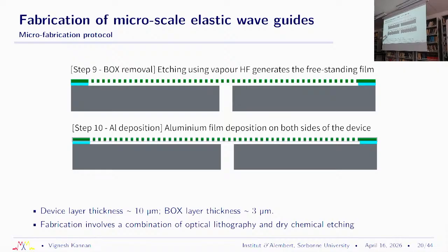Okay, so we end up etching the top surface, and it turns out that you can use hydrogen fluoride that basically gets rid of this intermediate box surface. So hydrogen fluoride, turns out, reacts not with the silicon, but with the silicon dioxide. And so what you end up with is a freestanding film with a 2 to 3 micron gap between a handle layer and the device layer, as we call it, where you can have whatever architecture you want in a freestanding surface. This is different from people in microelectronics where they would etch devices directly onto your wafer. And the problem or the challenge with these is you do not get complicated bending modes if you simply have patterns etched onto a large substrate.